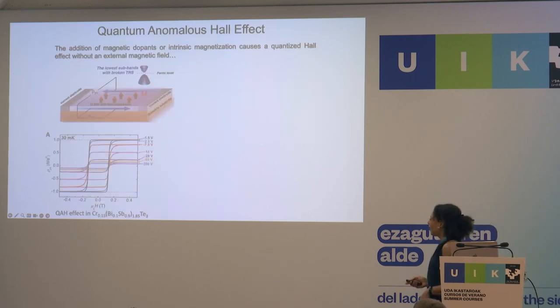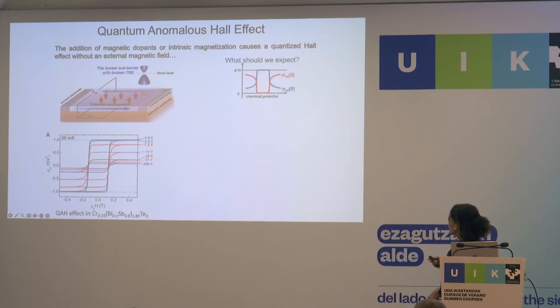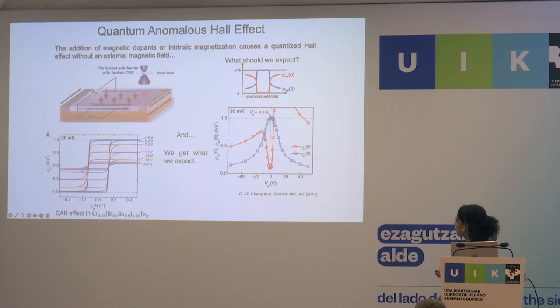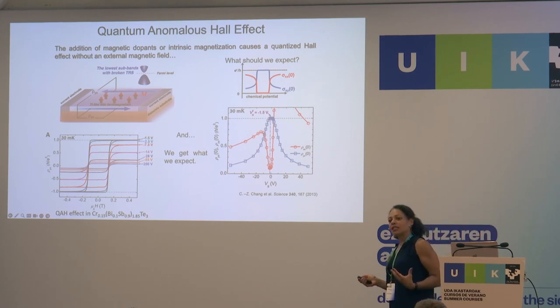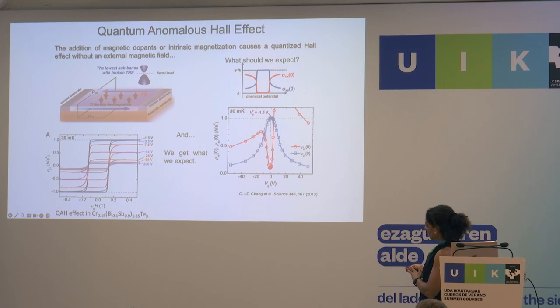This is the first experiment. I'll just say one thing about this, which is that when you look at the data here, the reason that this is very, very convincing experimentally is that you see at zero magnetic field, very clear Hall conductance, even with zero external field, right? And that resistance levels off at h over e squared at low temperatures. And if you look at the RXX and RXY, you should see the RXY go up to h over e squared and the RXX drop to zero.